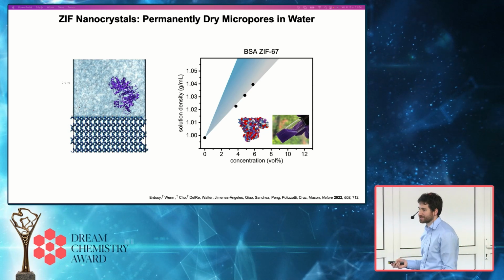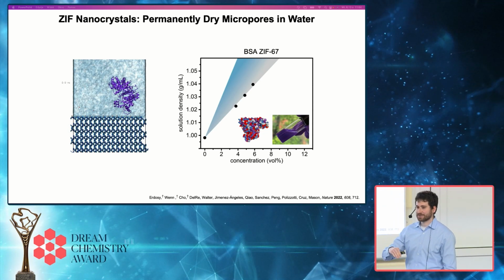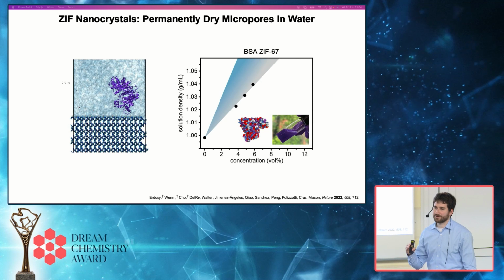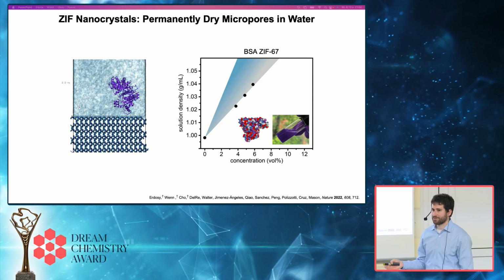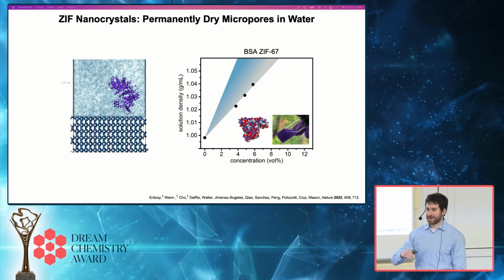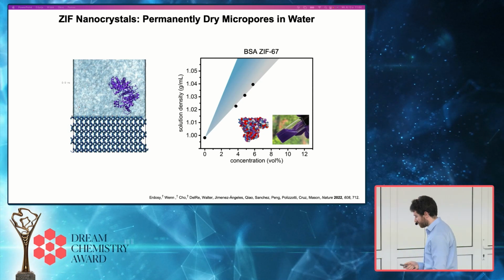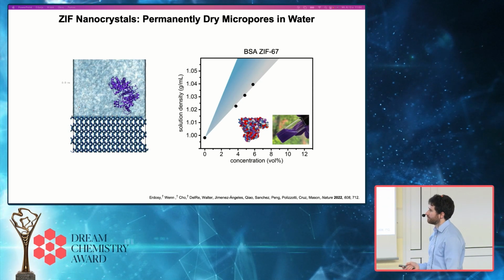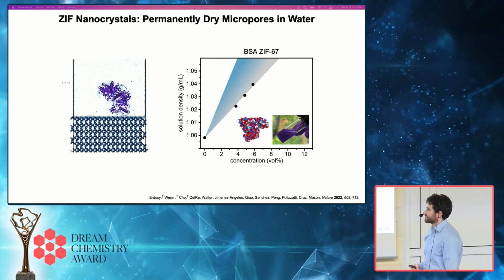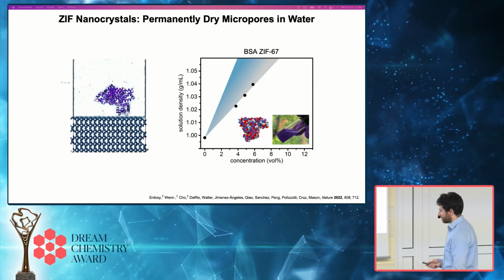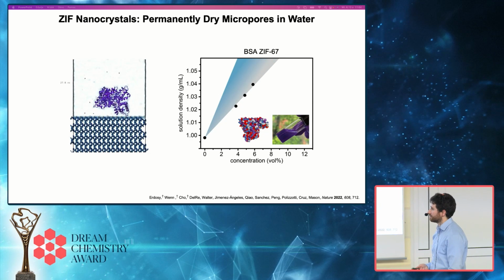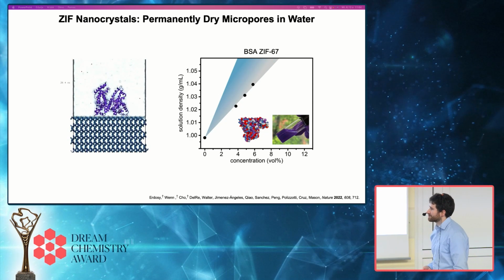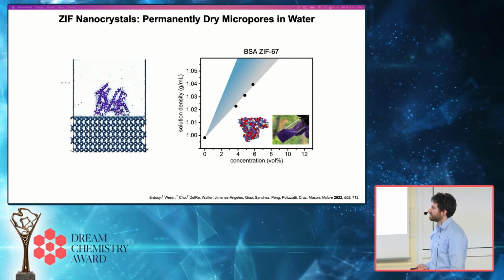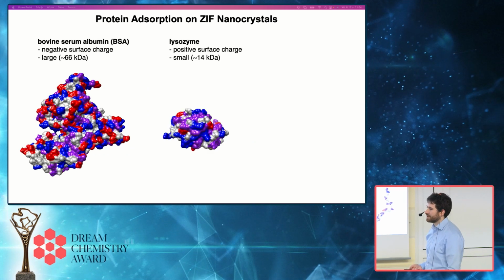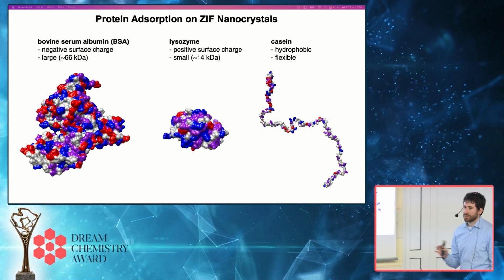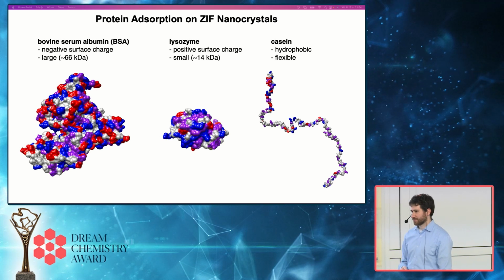And so one of the things we want to do is just better understand how proteins interact with these external surfaces so that we can either use that to bring new properties to our dispersions or try to prevent it through different functionalization approaches. This is just an example of bovine serum albumin, which sticks really strongly to the external surface of these ZIF particles. Some of the interesting things we found is that depending on the identity of the protein, so both its surface charge and size and structure, we see very different properties that can be induced in our dispersions.